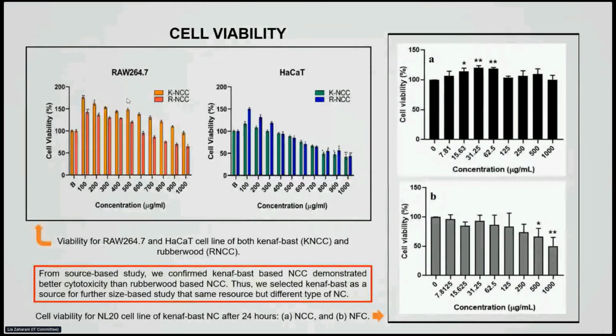Most studies showed nanocrystalline cellulose and nanofibrillated cellulose to have a negligible cytotoxicity effect, but the various types of cellulose biomass sources and the synthesis process of nanocellulose may affect cell viability. In this study, RAW 264.7 and HaCaT cells were exposed to different nanocrystalline and nanofibrillated cellulose concentrations for 24 hours, and cell viability was analyzed using the MTT assay.